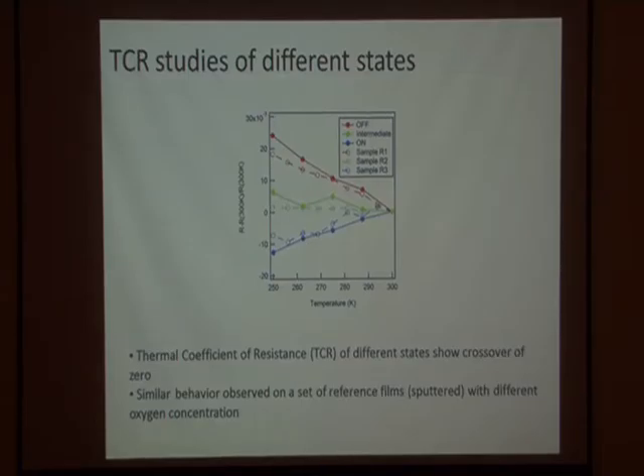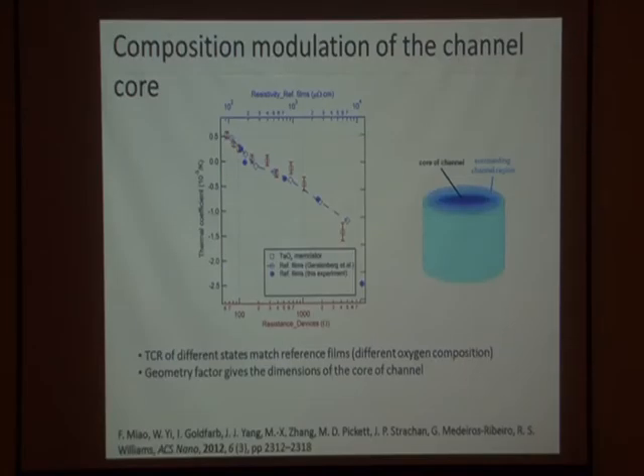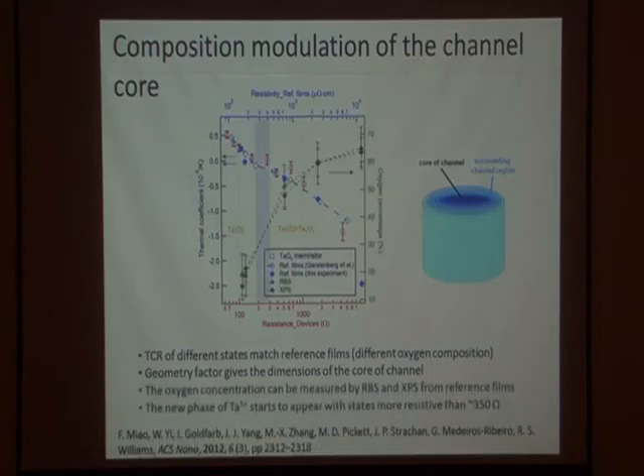And the definition is this: at zero temperature, if you look at the density of states, it's finite. Then you say, all right, it's a metal, but you try to measure current, nothing goes through. Why? Because you have little beads of metallic islands that don't talk to each other. So this is the Fermi glass, and this is what we found this year. So this is showing how we can modulate the composition. It's a very interesting paper, interesting to me, right, that we published, showing that we can modulate the conductance.